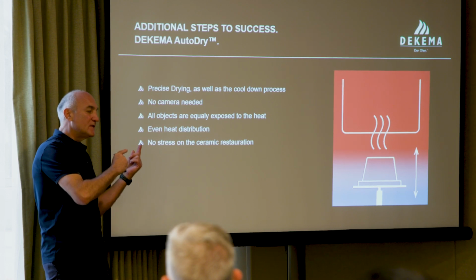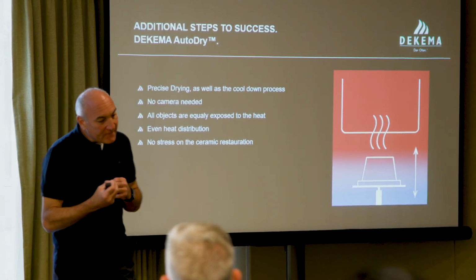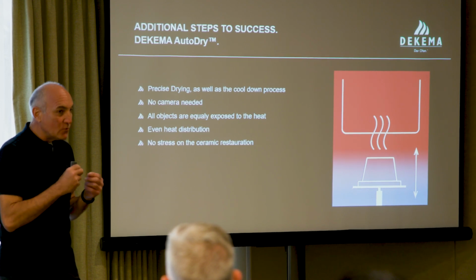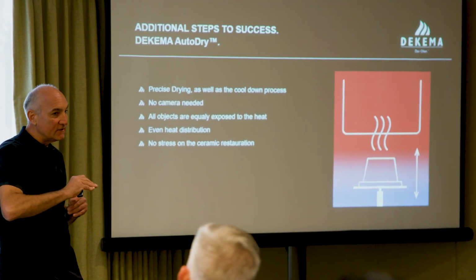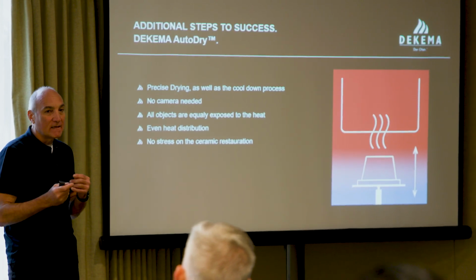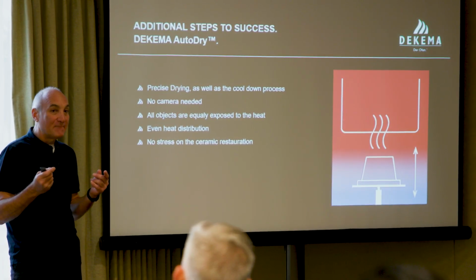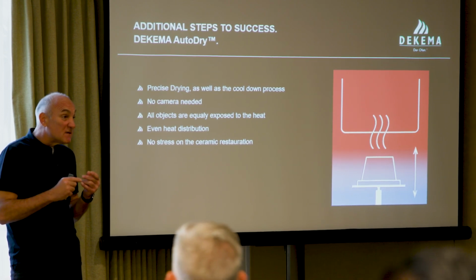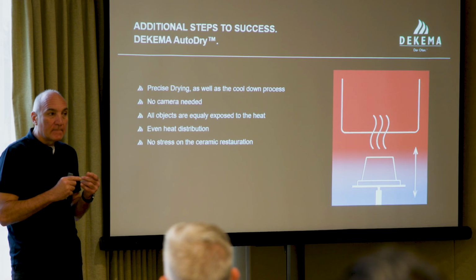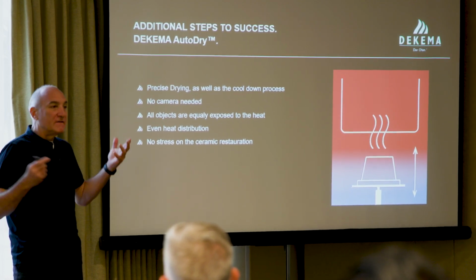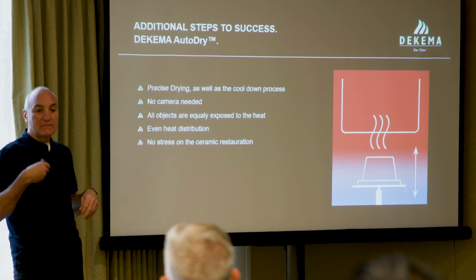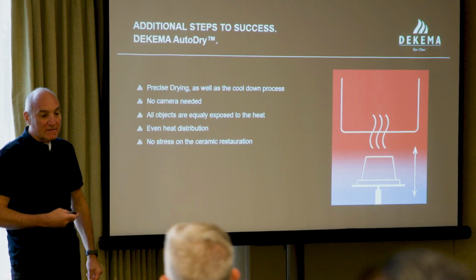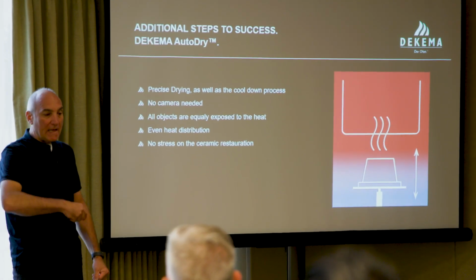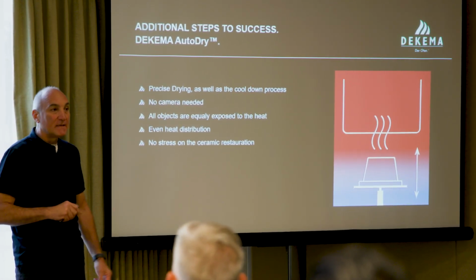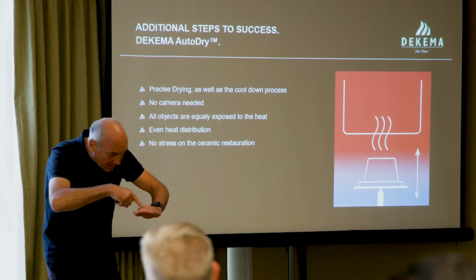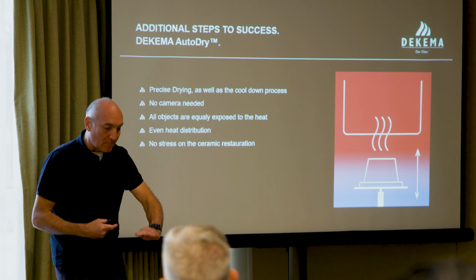Coming back to MOSI, MOSI is brittle. With a MOSI furnace, even if it's fast, you have to wait and cool down to less than 200 degrees before you start the next subsequent cycle. So a fast furnace can be quite slow if you have to wait till it's down to 200 degrees. With a DEKEMA furnace, if it's still 600 degrees, 800 degrees, we don't mind. If you want to start a subsequent cycle, the cycle tells you start with room temperature and go up to 700 degrees with 60 centigrades per minute. We will move the lift the way that the zirconia sees 60 degrees per minute by moving the lift.